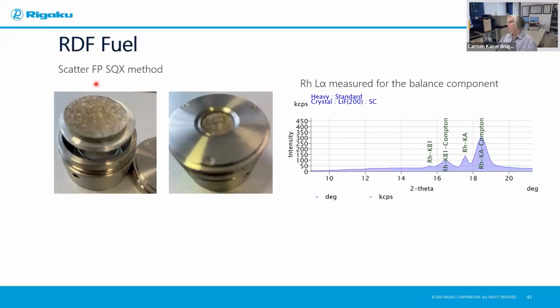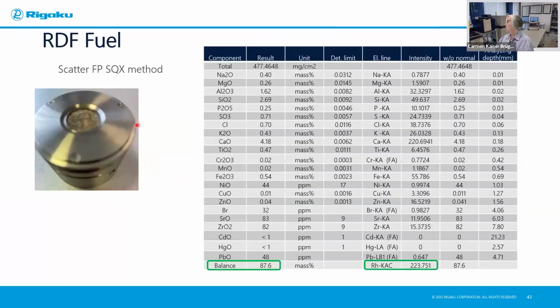Okay, here's another example of a refuse-derived fuel using the scattering FP. So you can see, once again, we're using the rhodium K alpha line for the analysis of the balance. So the scattering FP method here yielded a balance of 87.6%, using the rhodium K alpha Compton line. As you can see, the results are expressed here as an oxide.